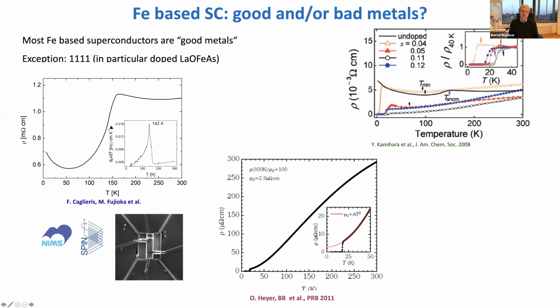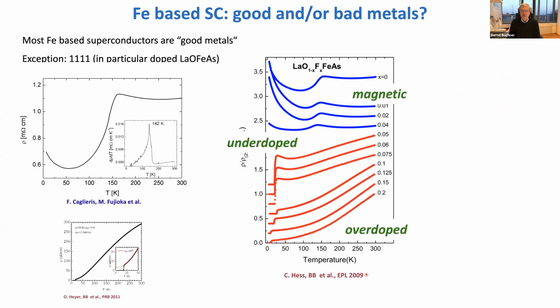And this immediately tells you that the scattering, which determines this very high value of the resistivity at high temperatures, is intrinsic. It's not extrinsic, or not only, mainly intrinsic. So you have a very strong intrinsic scattering, which is dominating the electronic transport, leading to the fact that these systems are very close to localization. And that's also what you see as a function of doping. This is very early data where you see that when you leave this magnetic phase, you still have in the so-called underdoped region this tendency to localization. Only if you go to very high doping concentrations do you end up with a resistivity which qualitatively looks like what we know from these very nice metallic systems.